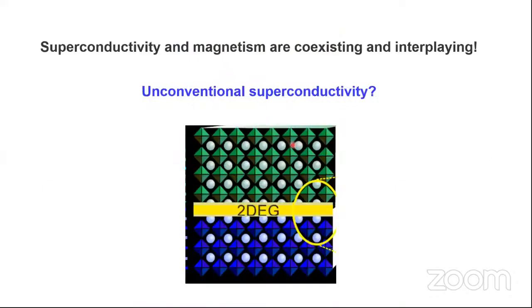But the difficulty here is that doing transport spectroscopy like scanning tunneling spectroscopy or point contact spectroscopy on the 2DEG is difficult because the 2DEG is always hidden underneath an insulating layer. So we found a technique to penetrate through this and make a contact with the 2DEG by using ultrasonic wire bonders and perform soft point contact spectroscopy.